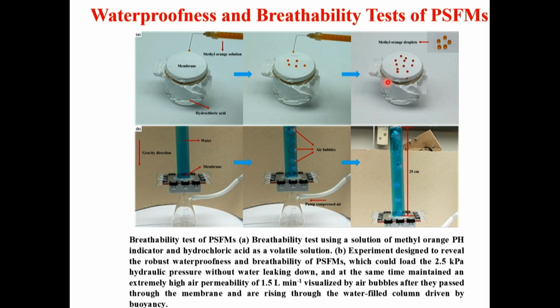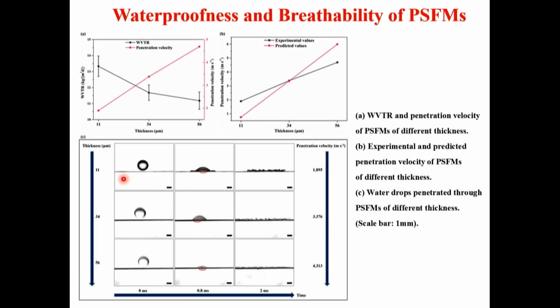So these membranes are not only thick enough, not only waterproof, but also breathable. That's already a good point. Now another experiment related to breathability is like this. You fill a column with a liquid and put the membrane underneath, and this membrane is also connected to a reservoir filled with liquid or with gas, for example air. Then the membrane holds the entire column of liquid, so the liquid is not leaking through. However, bubbles are going through the membrane, so it means that it's breathable for gas and fully impenetrable by liquid. So this is also an experiment which convinces that there are some good properties of this type of membranes.